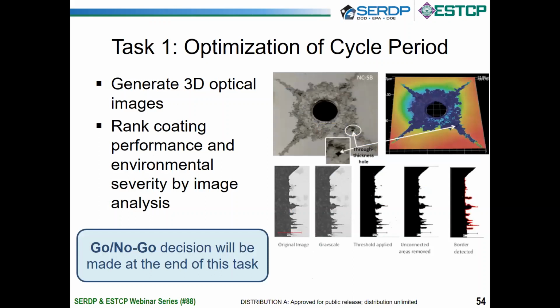So we're planning to assess the corrosion type and severity using optical profilometry. And then after that, we're planning to rank coating performance and environmental severity using that image analysis. At the end of this task, we will reach a go, no-go decision based on whether or not we've been able to correlate and provide representative corrosion types and extents that we can see in outdoor field exposure, but at 1,000 hours of accelerated corrosion testing. And that the results from this accelerated corrosion test provide an ordinal ranking of coatings that we would also provide using outdoor field exposure. Next slide, please.